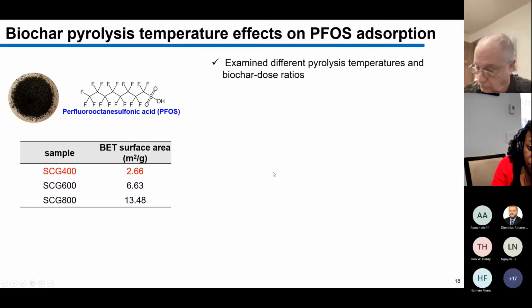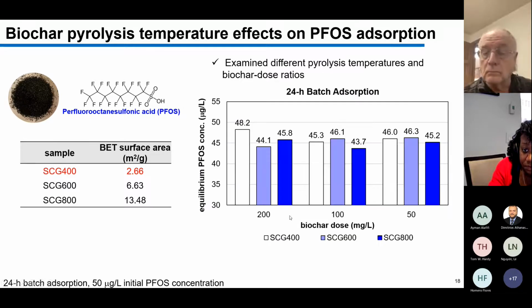Okay, so first we examined, again, the different pyrolysis temperatures and the ratios of how much biochar is present in our reaction systems versus how much PFOS is present. So we did a 24-hour batch adsorption test where on the y-axis we're plotting the measured equilibrium PFOS concentration in solution. On the x-axis we're plotting the dose of biochar in the system. So here it's from highest to lowest dose, so 200 milligrams of biochar per liter of reaction solution that contains the PFOS.